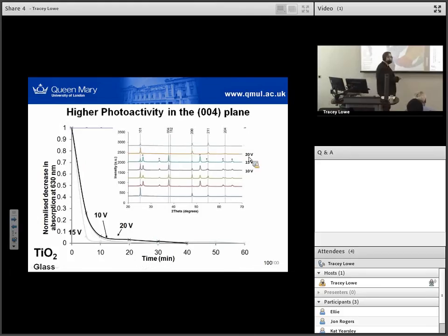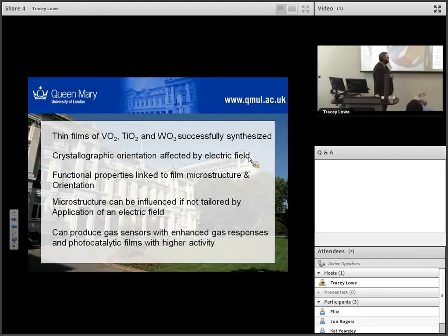Actually this correlates quite well to these changes in this 004 peak, or the appearance of this 004 peak. There have been a couple of papers which suggest that this is actually a very good surface to have your charge on—to stabilize your electrons on, to prevent recombination. So the fact that we can produce films which apparently have more of this surface available means that we can get better photocatalytic activity.